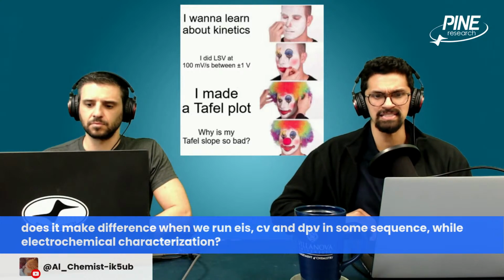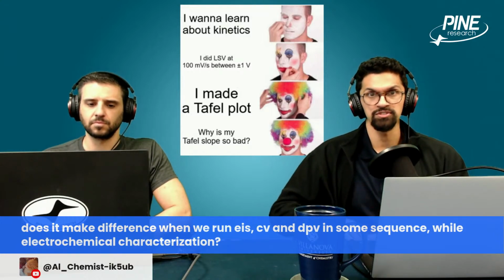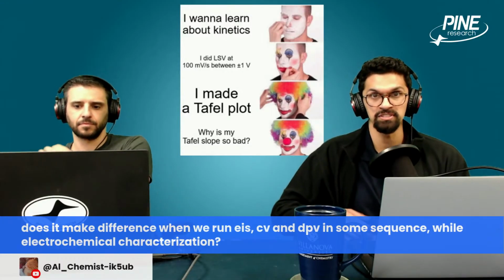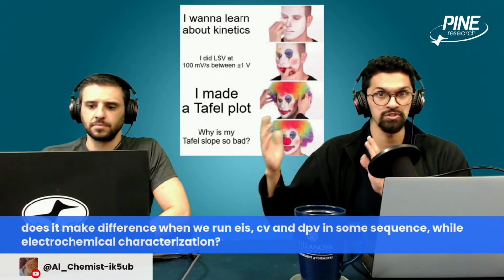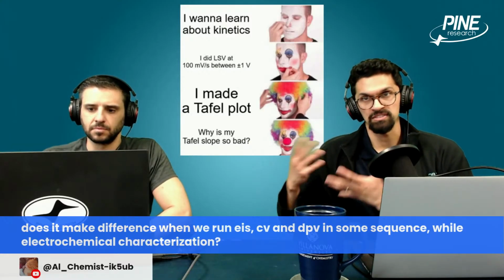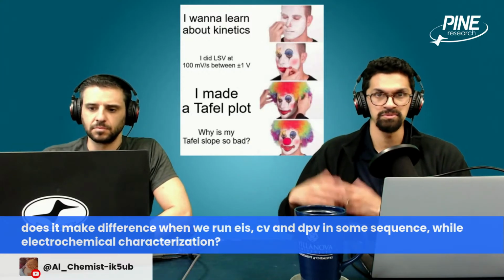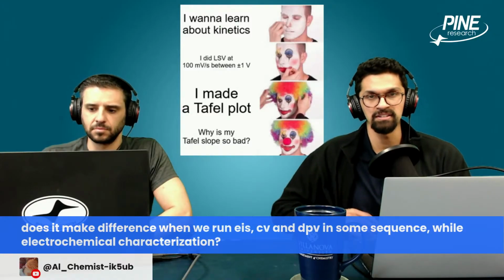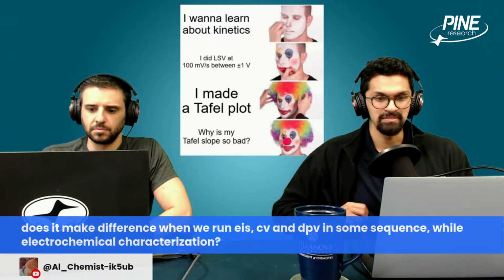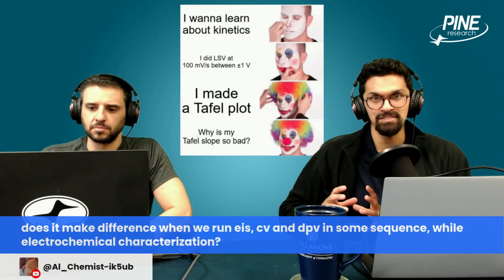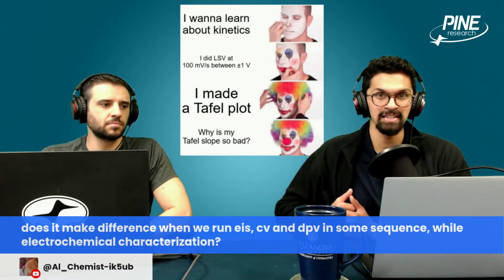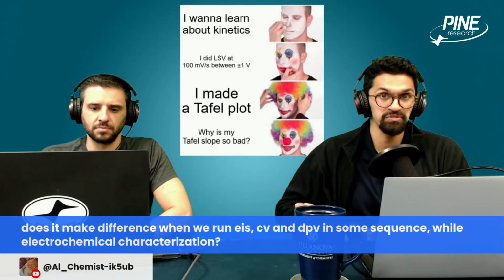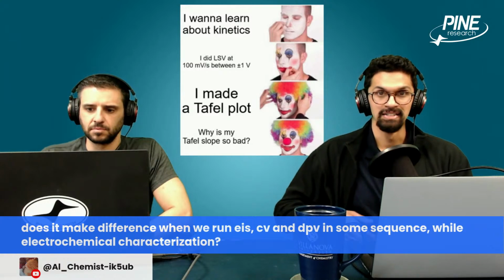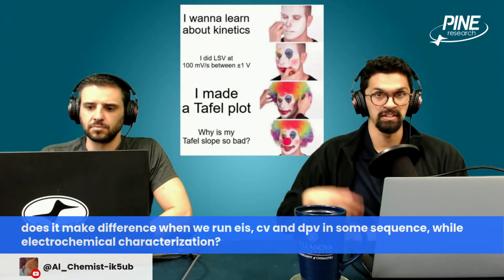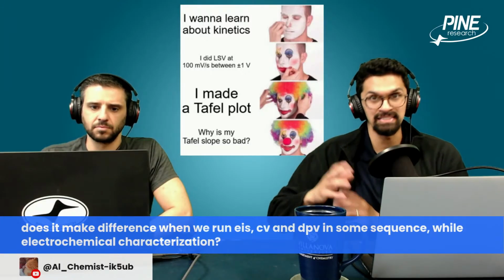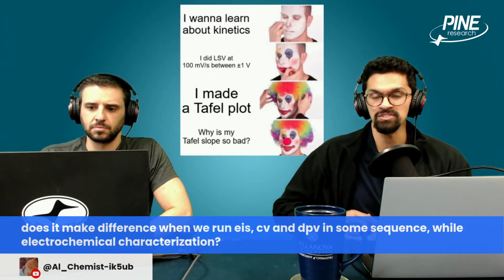But when you do techniques like CV and DPV, both of these are actively changing the potential of your system, usually over a fairly large or wide range. You're doing an oxidation reaction, you're doing a reduction reaction, you're doing various charging of the electrochemical double layer, or electrical double layer. And if you run EIS, do CV, and then run EIS again, you may have changed your surface or your system a little bit. You may have irreversible adsorption of your molecule on the surface, and that did something to your system where the EIS has changed.